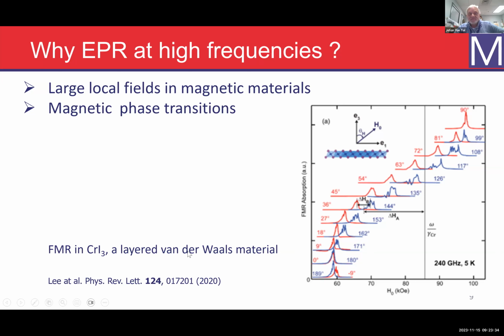And these are van der Waals materials in the sense that you can exfoliate these, and so they have some interest for spin manipulation and spin Hall effect, to get interaction with the external field if you make thin films of these kinds of materials. And of course, there is an orientation dependence. Part of it is actually due to the shape of the sample. So if you have a thin film, you expect this. But part of it is also due to the anisotropic exchange, and in this case, the Kitaev interactions as well.